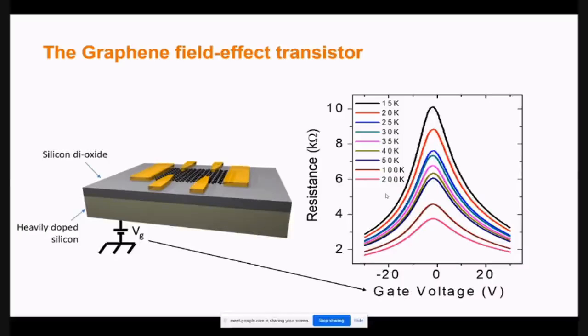Now, once you have a device like that, you can make a field effect transistor. The original graphene paper was actually a demonstration of a field effect device, in which you use heavily doped silicon and apply a voltage on it, with the silicon dioxide layer acting as a dielectric. So the graphene layer on top is capacitively coupled to the gate, and you can change the electron density or the hole density. If you make the gate voltage positive, you induce electrons, and if you make the gate voltage negative, you induce holes. In both cases, the charge density goes up and the resistance comes down. So that's the field effect device that one is talking about.